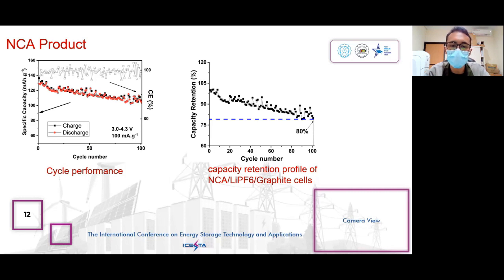At the current rate of quarter C, the specific discharge capacity of the cell is about 110 mAh per gram, which is 91% compared to capacity tested at 0.1 C. At the end of the cycle test, the specific discharge capacity of the cell is about 88 mAh per gram, which is 80.1% compared with the starting capacity.